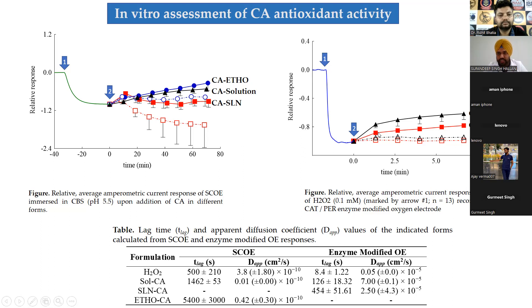With this modified electrode, SLN showed good activity. The possible reason is that skin presents great resistance to the movement of particles and formulations across the membrane — the formulation needs to interact with skin lipids and proteins before facilitating diffusion into deeper layers. Comparing both techniques, in the absence of skin the response was very quick and recorded in a short time frame, whereas with skin the response extended up to 70 minutes.